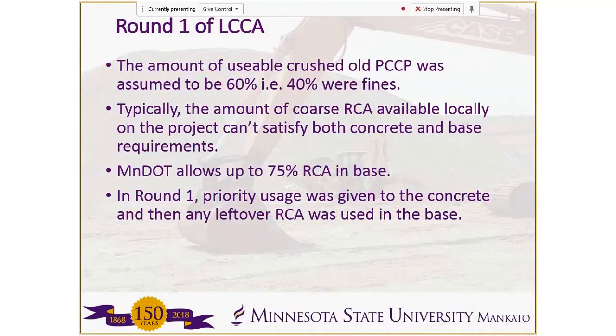Typically, when you crush old concrete pavements, you get about 40% fines from that and 60% coarse. So the amount of usable concrete aggregate was about 60% from crushing. So I mentioned we had old concrete pavement which we assumed was crushed up. So about 60% could be used as coarse aggregate. The remaining is fines, which we're not going to be using in the mix.